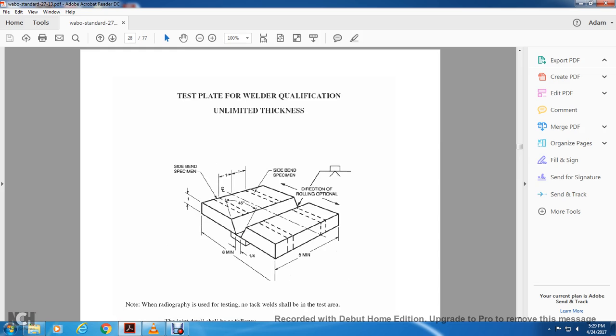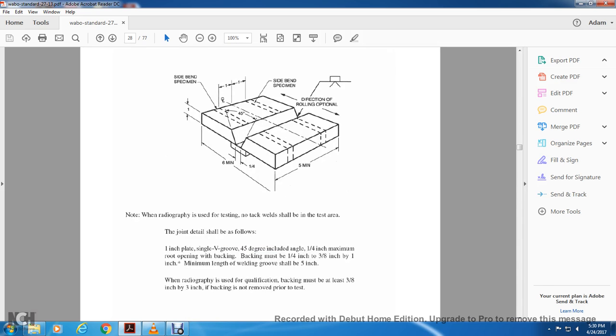All right, test plate for welder qualification, unlimited thickness, side bend specimen, 1 inch by 1 inch, 45 degree angle, 6 inches minimum, 1/4 inch, 5 inches, side bend specimen, direction of rolling optional. When radiography is used for testing, no tack weld should be used in the test area.